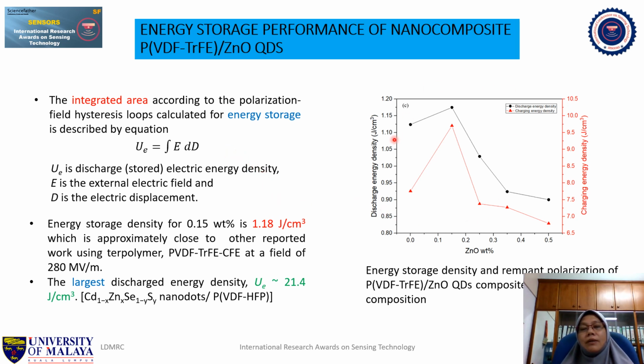So from this figure, we note that the highest energy density for this polymer nanocomposite is achieved when the zinc oxide composition is around 0.15%. So the energy storage density is around 1.18 joule per centimeter cube, which is close to what has been reported by other workers using the polymer VDF-TrFE CFE at 280 MV per meter. The largest discharge energy density reported is around 21.4 joule per centimeter cube.